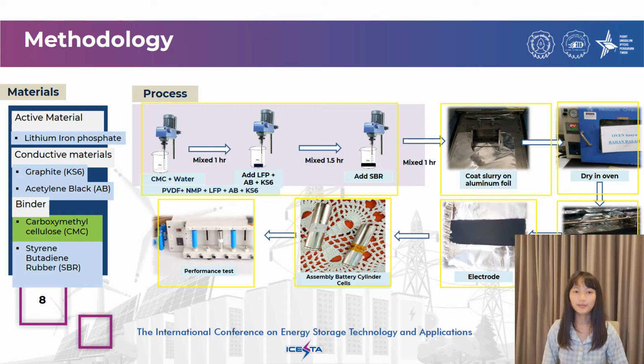The experimental process starts with preparing the substance by weighing out the material at the correct ratios. Next, with a mixer, I start by combining CMC with water for 1 hour, then add LFP, AB, and KS6 and mix for 1.5 hours. Then lastly, add the SBR and mix for 1 hour. The cathode production using NMP had the same active and conductive materials, but used a different binder, PVDF.